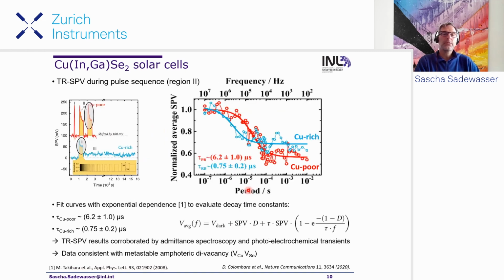So now the question is to analyze these behaviors a little bit more. So we plot this as a function of the period or the frequency. And we see that there is this transition from, let's say, the full SPV to about half of the SPV, which is what you expect because we use a duty cycle of one half. So the average SPV for fast enough pulses is going to be half, for slow enough pulses is going to be close to full.